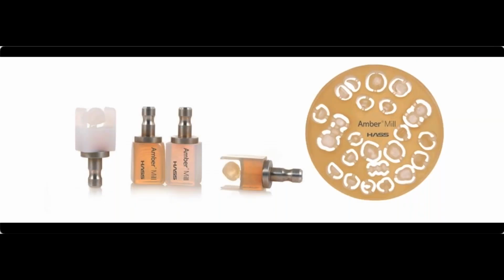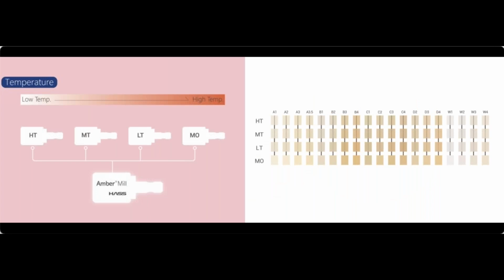The company from Europe has released a lithium disilicate that is interesting on the shade side, because if you use Emax, you know that you have your shades A, B, C, 1, 2, 3, but you also have high translucency, medium translucency, low translucency, and medium opaque, right? So if you want to store this in your office or the laboratory, there's so many options. When in reality, companies always knew that translucency is just a matter of which temperature you choose to sinter, to bake this restoration. And the company said, listen, I don't want to oversell you this. I'm not going to sell all these different translucency kinds of blocks. I'm just going to tell you what temperature you put in the oven, and then you can achieve the translucency that you want. So I think that was pretty cool.